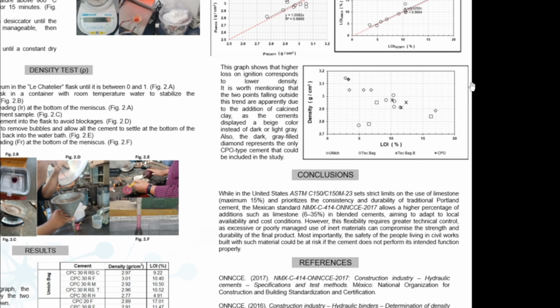This graph shows that higher loss on ignition corresponds to lower density. It is worth mentioning that the 2 points falling outside this trend are apparently due to the addition of calcined clay, as the cements displayed a beige color instead of dark or light gray. Also, the dark gray-filled diamond represents the only CPO-type cement that could be included in the study.